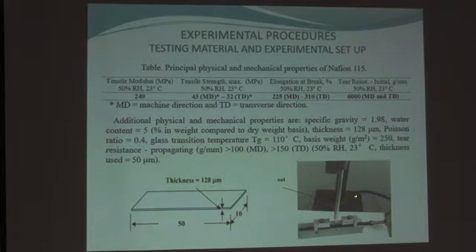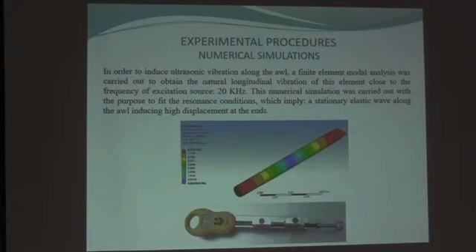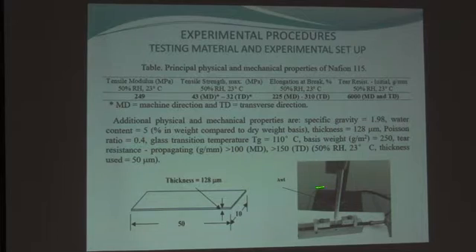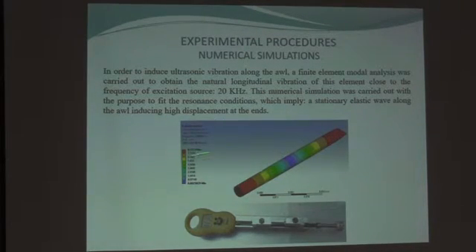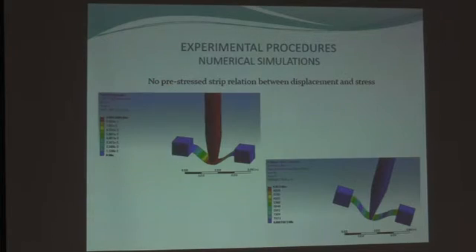And the setup is, as you see here, that here is the strip. This is the self-constructed equipment in order to apply a tension in the strip. And perpendicular is the horn connected to the ultrasonic fatigue machine. In fact, the element calculated to fit the resonance conditions is not the strip, but the horn communicating the vibration loading. Here we have calculated the horn, which presents a frequency close to, it's not clear here, 20,060 Hz, very close to the frequency of excitation, 20 kilohertz. And here we have the self-constructed equipment allowing us to apply stress in the plane direction in order to prepare the specimens.